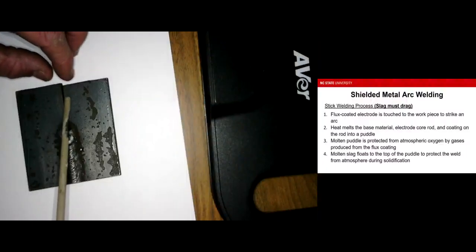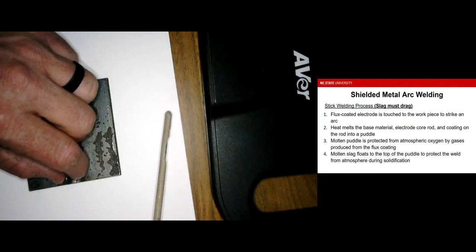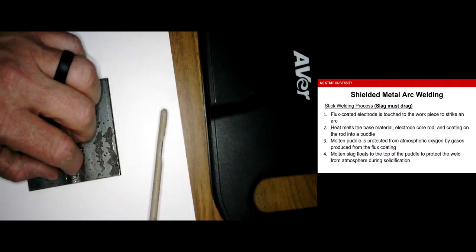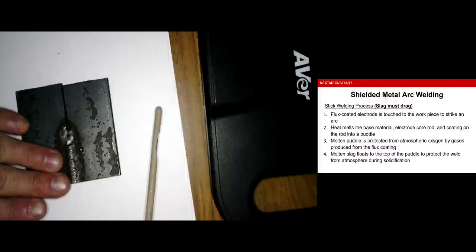Now, the reason that you must drag this puddle is because as this begins to cool off as we weld, you'll see this substance float to the top. This substance that kind of floats to the top, it'll float there and then it will solidify. And that's called slag. And slag is the impurities within the metal and other impurities within the weld that float to the top of that joint. And it also provides a little bit of insulation for the weld to cool.